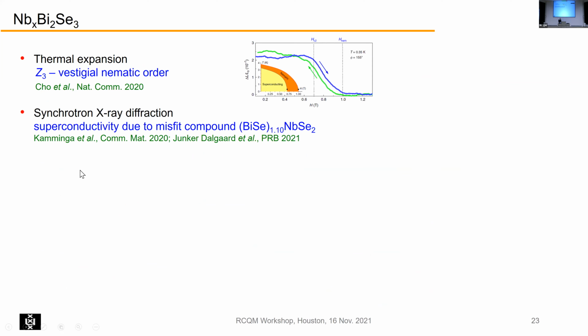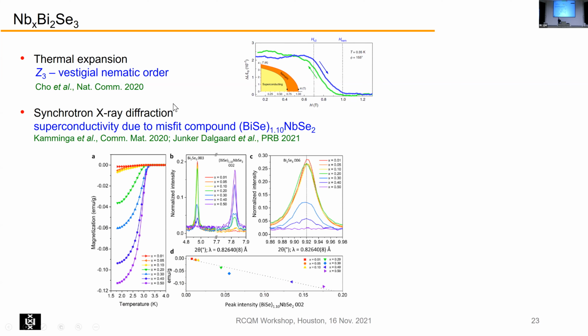However, a very interesting experiment was done by Kamminga, with synchrotron radiation. They looked very carefully at the structure of this niobium intercalated bismuth 2 selenium 3, and they found that, depending on how you prepare the sample, a fairly large amount of a misfit phase can be present. The misfit phase is this one here, and that's also superconducting on its own. Here are X-ray diffraction peaks. This is for the misfit phase, and this is for the bismuth selenium 3. These are different sample niobium concentrations. If this is large, you have lots of this, and you also have a large superconducting volume fraction. So here's a very clear link that it is actually the misfit phase which determines the physics in the niobium doped case.